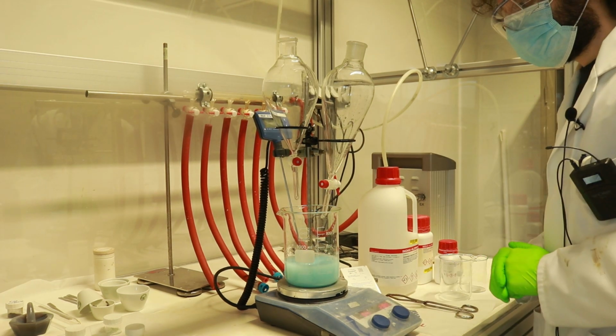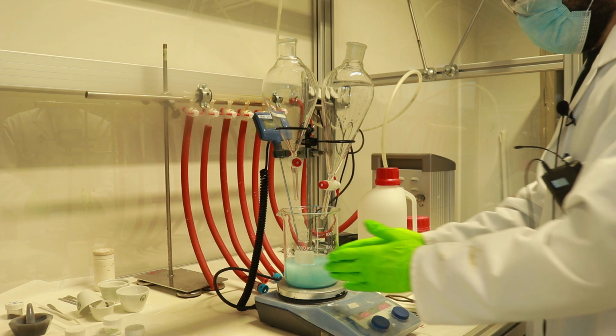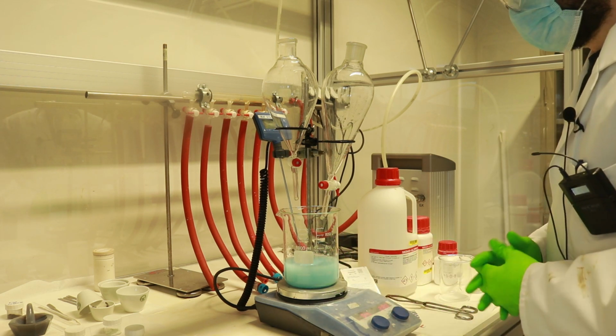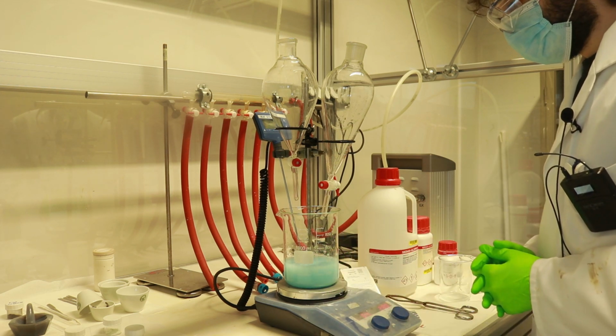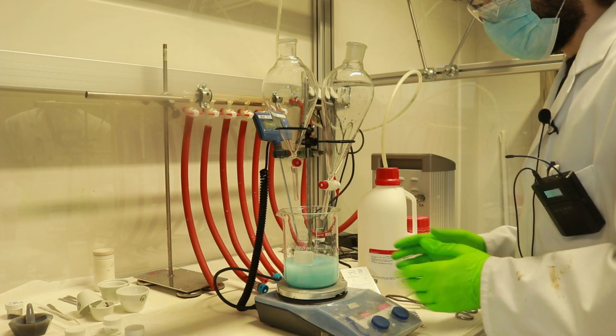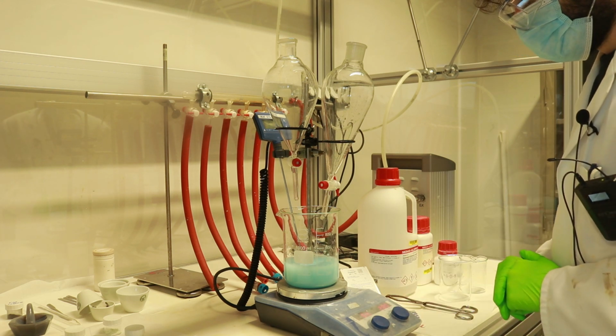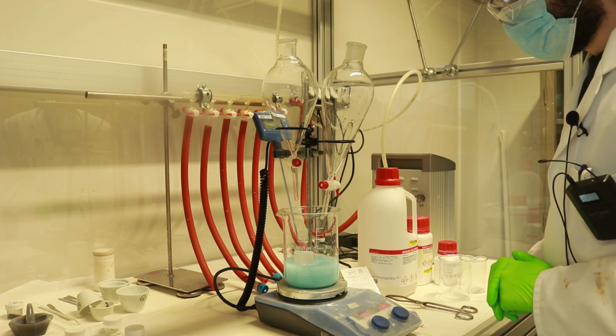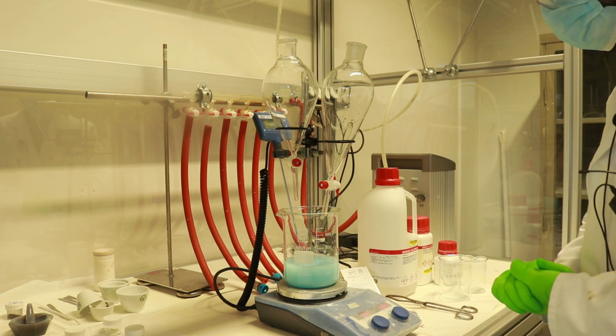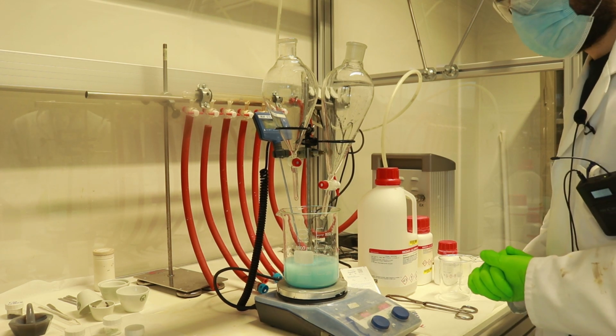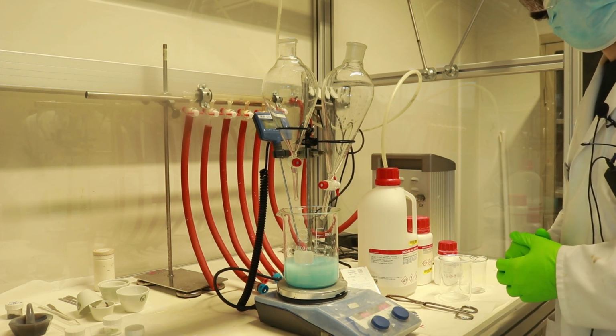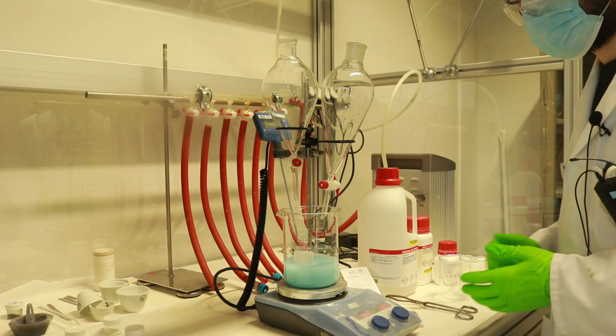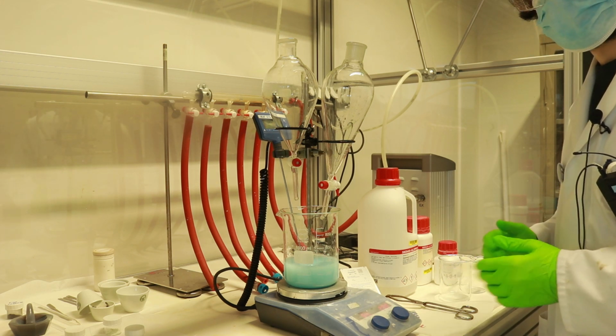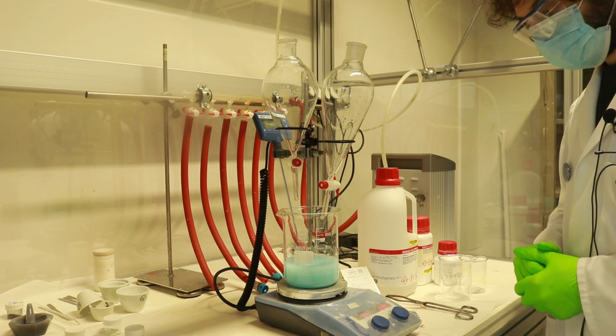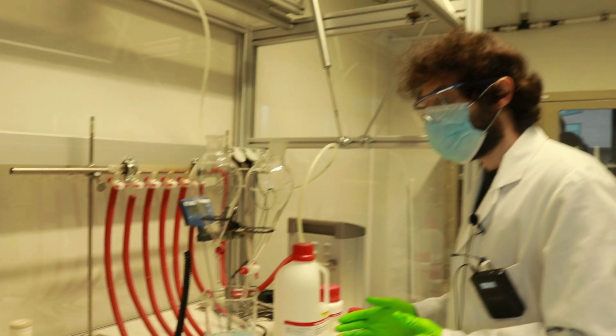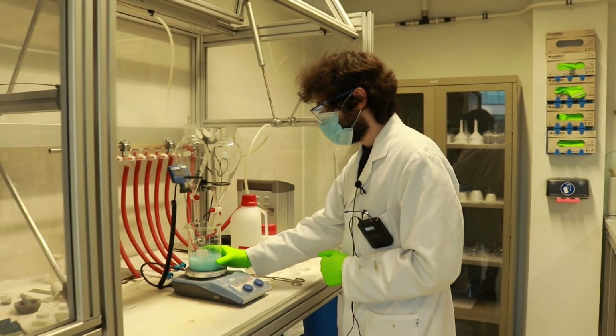Both solutions have been added into the beaker. We will now keep this solution at 30 degrees for 12 hours so that we can age it. The next steps after this would be to filter out the precipitated particles, washing them until they are at a pH of 7, indicating that we have removed most of the ammonium ions, and then finally drying and calcining them.